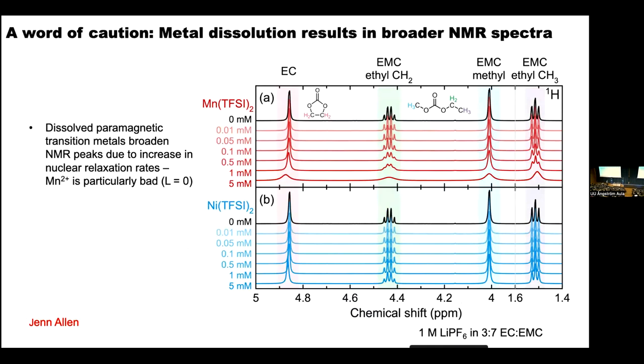So just a word of caution, we've also looked at the effect of metal dissolution, and this is some beautiful work of my former student Jen Allen, who looked at the effect of metal dissolution on the NMR spectra. And one of the things that, just for the NMR people in the audience, you have to be aware of is that when you put these paramagnetic ions in the solution, you start to broaden your peaks significantly, so you have to worry about what you're looking at.